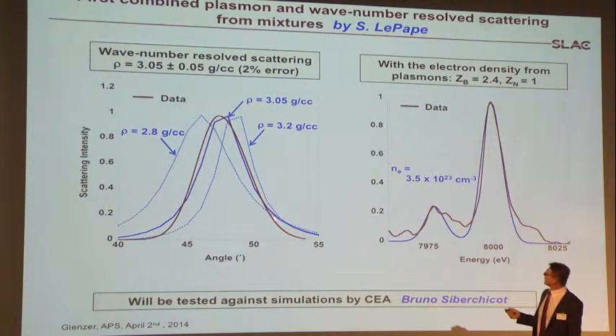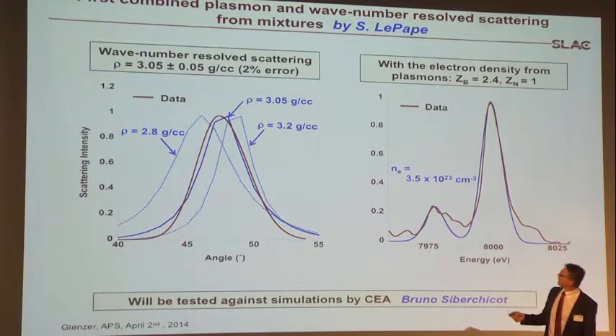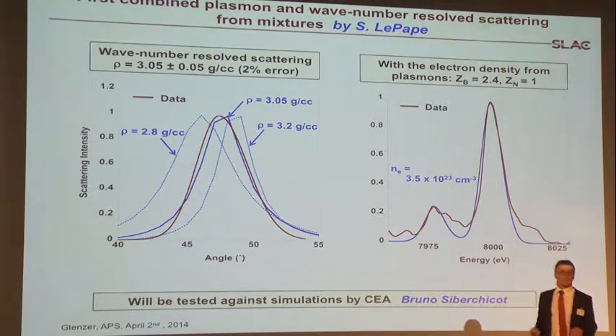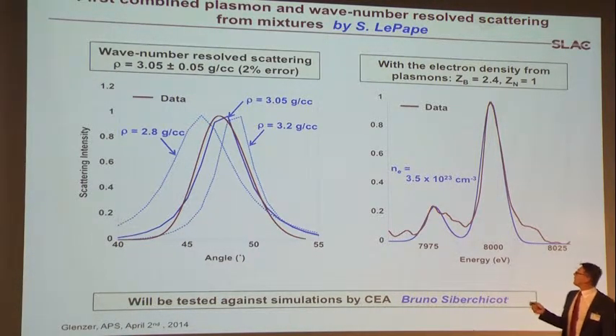This is boron nitride. The red, again, is the experimental data. And what we've done here, we look at our theoretical calculations and we fit this to the measurements. What we find is for a mass density of 3.05 gram per cc, we get a very good understanding of where the peak lies in wave number. And you can see how accurate this measurement is. If you look at 2.8 or 3.2 gram per cc, there's just no way this will ever agree with the experiment. So from just these measurements, the relative error is 2%. So it's a very accurate measurement of mass density.